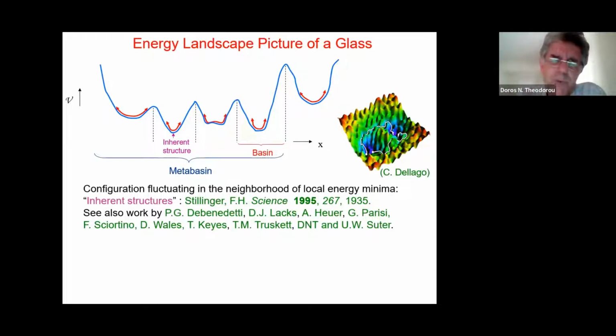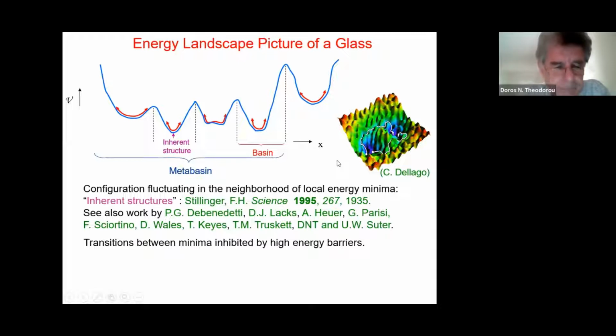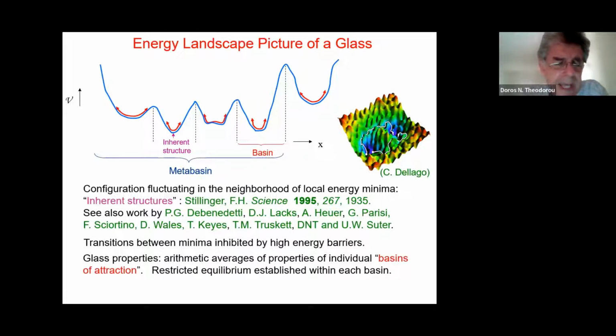In reality, we're speaking of 3n coordinates here of the full configuration space of the polymer, X. So transitions between different basins or minima are inhibited by high energy barriers. And if we have a real glass, we envision that its properties are arithmetic or quenched averages of the corresponding properties of the individual basins of attraction in which the glass is arrested. Of course, the distribution among these basins is governed by the history of formation of the glass. A restricted equilibrium is established within the basins and metabasins, but full equilibration is inhibited by the large energy barriers.